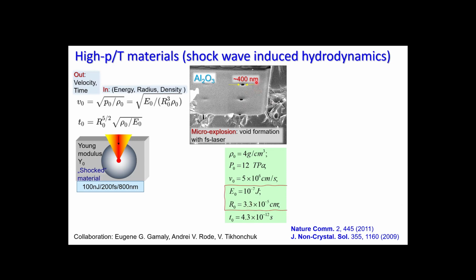And what we see after we open and mill the energy deposition site, and this is a single pulse, is that we see the void, and we can measure its geometry. Because pulses are very short, there is an invitation to look at this as a strong explosion. And strong explosion is how shock waves are generated inside the volume of material. So you need to know three parameters to calculate the two. So five parameters are describing your response.